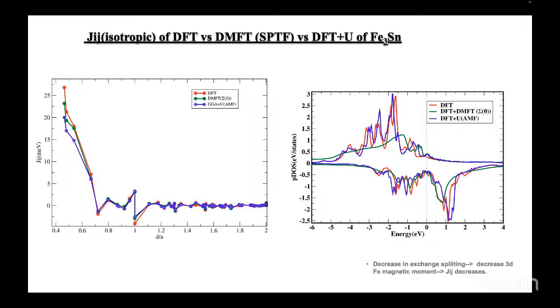Yeah, so because it is a DMFT plot, this broadening signifies the Fermi liquid renormalization, which comes into the picture when we account for the dynamic correlation. So the effect of dynamic correlation, one sees this renormalization of the bands coming from DFT plus DMFT, whereas DFT plus U just accounts for the static part of the correlation. So we see a slight change in terms of the shifting of the bands, in terms of orbital polarization coming. And the effect of this comes from how the exchange splitting decreases and the magnetic moments modify. So we see a decrease in the exchange splitting when we go from DFT to DMFT. That leads to a decrease in the magnetic moment magnitude, and in turn leads to a slight decrease in my JIJ strength.